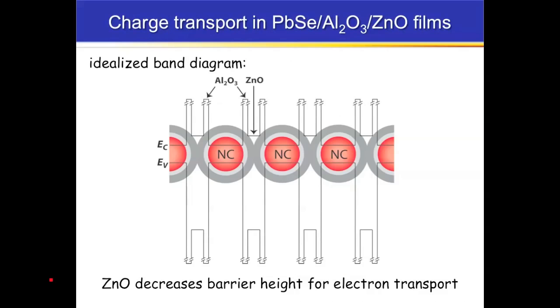And we think what we're doing here is that it's pretty well known that zinc oxide has a very nice conduction band alignment with quantum dots, with the lead selenide quantum dots. That means that the valence band alignment is very, very bad. And so we're basically lowering the barrier to electron transport between quantum dots, but not really lowering the barrier for hole transport at all. And so this is why we believe that the electron mobility goes up and the hole mobility really doesn't change very much. So we're playing these games with other kinds of semiconductors to alter the barrier heights and thereby control the mobility.